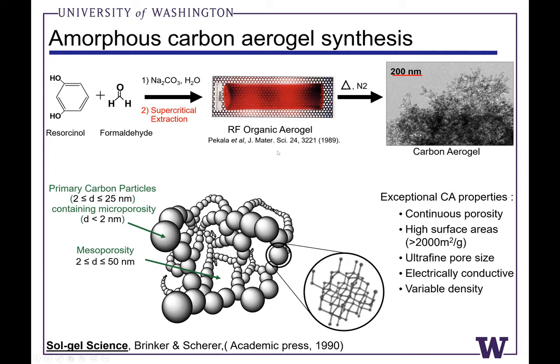We effectively use supercritical carbon dioxide to remove all of the water from the gel phase and effectively recover a hydrocarbon aerogel that we can then heat up. It's just a high temperature pyrolysis, maybe 1,000 degrees Celsius. And I like to say we drive off all the hydro. You can think of the H2O in formaldehyde. We try to remove all of the hydrogen and oxygen from the hydrocarbon precursor molecules we start with. And after pyrolysis, we're left with a very high surface area, amorphous carbon aerogel.